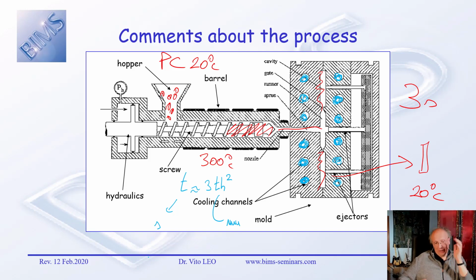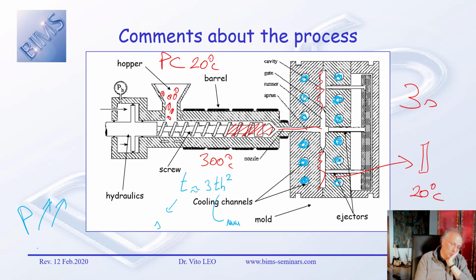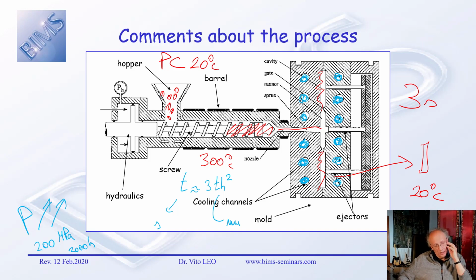And of course, if the cavity is thin, pushing a very viscous material through such a thin cavity is extremely challenging. So we do have very high pressure as a consequence. Okay, pressure is extremely high. That would be as high as 200 megapascals, which is 2000 bar, more classical units that we may relate to at the shop floor level. Okay, so we need to be careful with that. What happens to a molten polymer when you apply such a huge pressure? That's one particular aspect I will go through in this seminar.